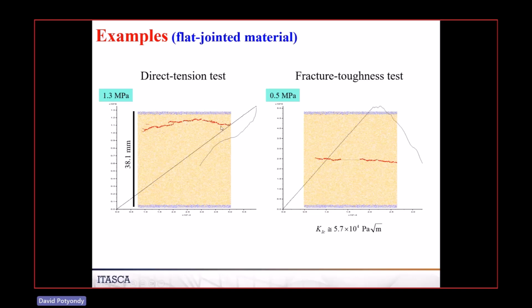Then we take this and do a direct tension test on it, and we can see we're getting a single fracture like we should. We're getting a very brittle response. We're seeing this snapback in the stress in the tension test because of the way we were measuring axial stress in this model: by putting a circular measurement region in the middle. Just think about what happens there. The stress is tension, tension, tension in the middle. And once it starts to break, this middle region relieves its stress, and not just its stress. That causes the stress to drop, but we're also measuring strain in that region.